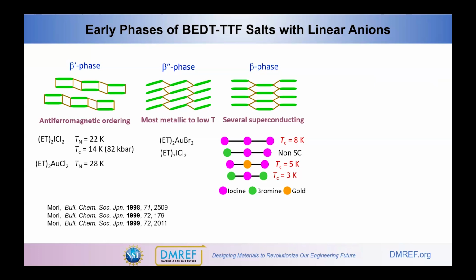The early phases with linear anions are what's called the beta prime phase. These are dimerized ET molecules that generally exhibit antiferromagnetic ordering, like ICl2, which has a temperature of 22 Kelvin. Under 82 kilobars of pressure, it does undergo a superconducting state at 14 Kelvin, probably the highest TC for an ET-based superconductor.